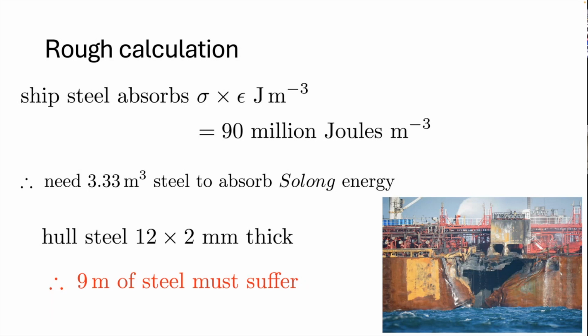That simply isn't true, for example, for graphene. When you break it, you recover all the energy elastically, and in any case, graphene loses its strength as soon as you scale it up. So the ability to absorb energy is really to do with the metallic bond of steel, because you can have layers of atoms sliding over each other without actually disrupting the bond at all. And this principle comes into your everyday lives.